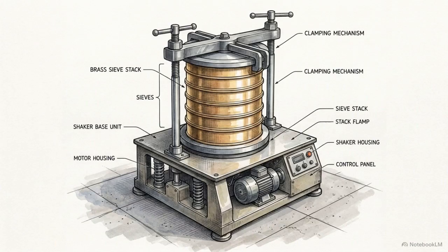The sieves stack in descending aperture size, sorting sand coarsest to finest. The solid pan goes at the bottom, followed by the 75-micron sieve, increasing to the 10 millimeter top layer. Pour the dry 1.2 kilogram sample inside and secure the lid. Place the entire stack into the mechanical sieve shaker and tighten the clamps to hold it in place.